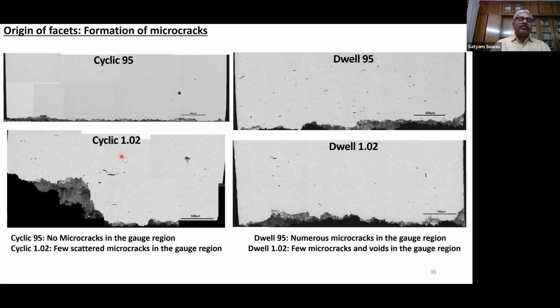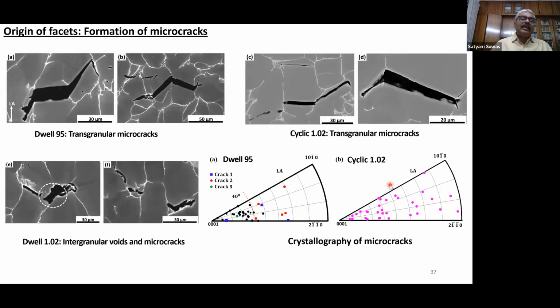We also polished the sample and saw the crack formation. Again, for cyclic condition, if we consider load as a parameter, we could see here that there is more propensity of cracking or crack initiation in the case of higher loaded samples. And for dwell, again, for the same load, dwell shows more number of cracks. So this is a very clear observation. We analyzed these cracks carefully and we saw the orientation. These were subjected to EBSD investigations in those regions, very carefully picked up, and then we measured this.